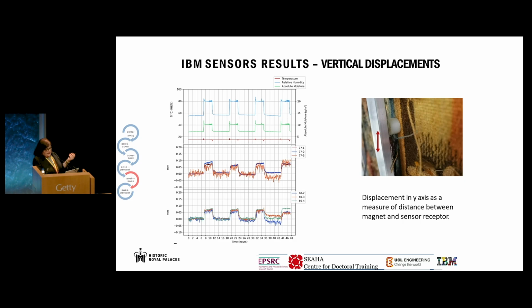However, for direct comparison with the DIC results, we reverse the sign from the results of the IBM sensors so you can read them more easily. So for the 15 degrees centigrade, the measurements followed similar behavioral patterns as with vertical strain DIC results.